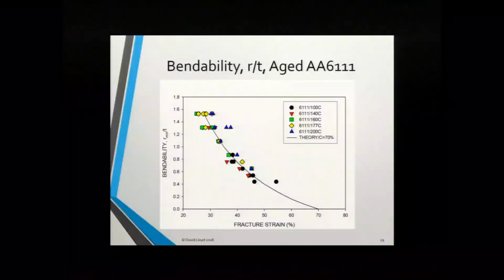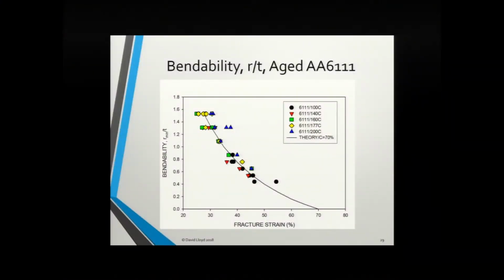This is some data for aged material. We've shown a lot of data in the literature, in papers that we published on T4 type materials. This shows that the equation also holds very well for aged material. And this is 6111, and it's been aged over a range of conditions. This is the data, and that's the theoretical line, using 70 as the constant.